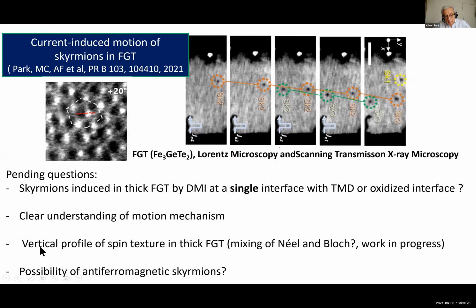For example, the problem is exactly what is the vertical profile of the spin texture in thick FGT. So my idea is that certainly there is a Néel skyrmion at the top, close to the interface, and then a progressive transition to Bloch skyrmions. And the exact profile is not well known, and work is in progress to really determine what is the vertical profile of these skyrmions, because Lorentz microscopy sees mainly what is on the top and ignores the facets with the beam of electrons. It's not possible to see the Bloch skyrmions. So there is some pending problem to solve.